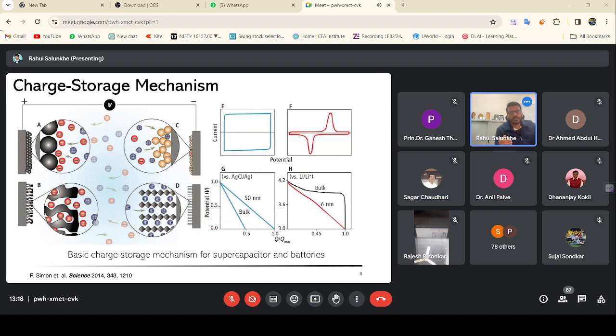These kinds of materials can have certain redox reactions, and because of that the charge gets stored. The disadvantage is that as a certain number of redox reactions are continuously occurring on the surface of the material, after certain cycles the performance of these materials gets degraded, and these capacitors quickly get discharged after a certain number of cycles. So their performance cannot be retained over a long time, as we have seen in the case of electric double layer capacitors. There is another type, intercalation and deintercalation type materials, where the ions get intercalated and deintercalated and the charge gets stored. So these are the basic charge storage mechanisms possible for supercapacitors.